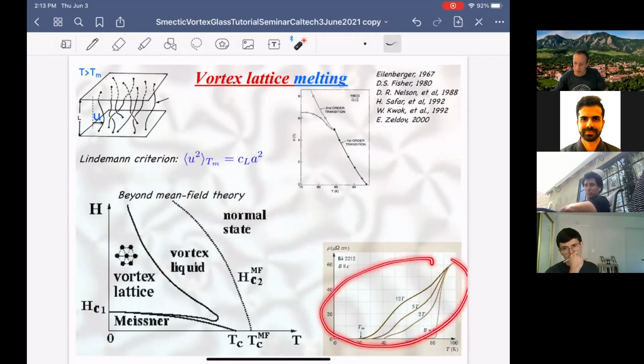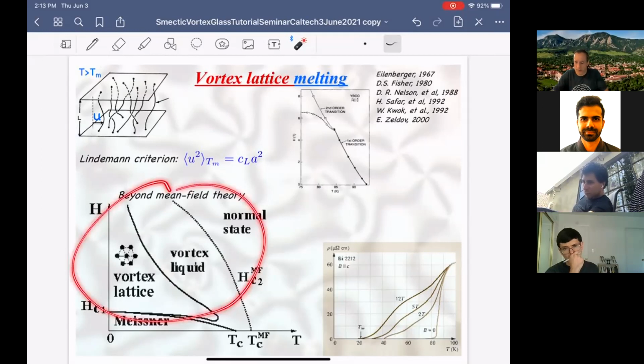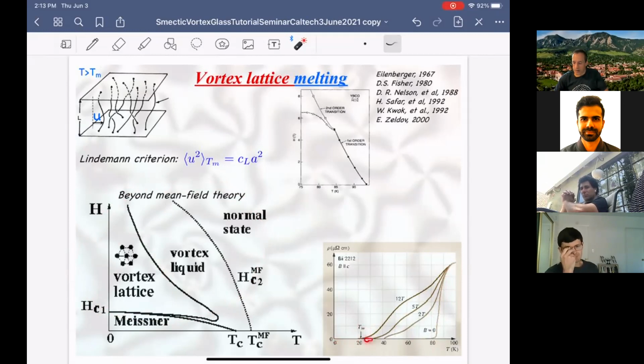In terms of resistivity, and there are many other phenomena that follow from this enrichment of the phase diagram, the behavior is quite striking. In zero field, you have a nice sharp phase transition at the critical temperature, let's say here, 80 Kelvin. But when you put on a magnetic field, the place where resistivity actually vanishes is far lower. There's a large intermediate region that's magnetic field dependent, where the resistivity is non-zero, though there's a precipitous drop compared to the normal state value, and that's associated with this vortex liquid state.